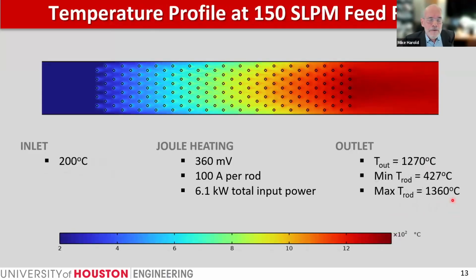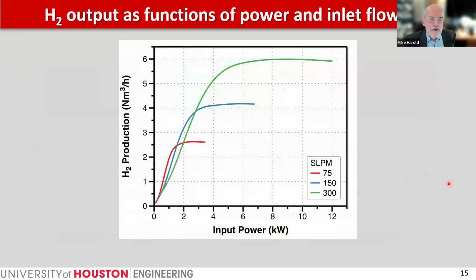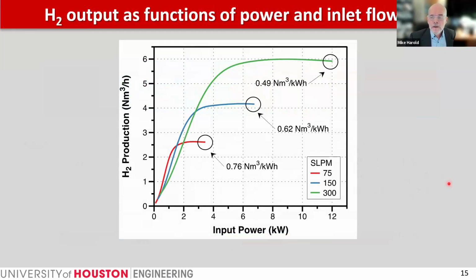You can see, and this is to be expected, we have the heating from 200 degrees to a much higher temperature. The highest temperature we see in this particular simulation is 1360 centigrade. The minimum wire temperature is 427 degrees centigrade. So there's heating from left to right. Reaction is occurring along the length. Now here's the hydrogen productivity versus input power for 3 different flow rates. And as you would expect, the more methane that we put in, as long as we provide enough power, the more hydrogen we produce. And it kind of peters out because of equilibrium limitations that I've described.